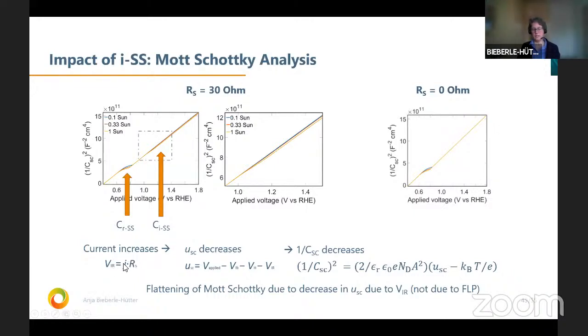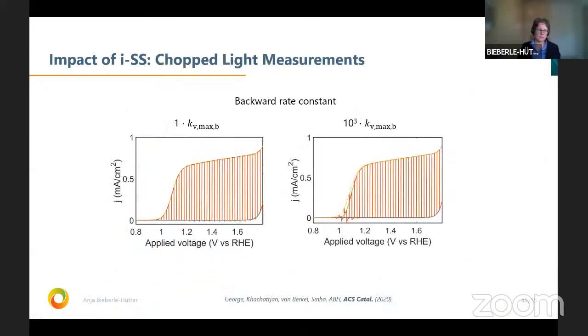So actually, when we have a serial resistance and the current density increases, we actually increase the space charge potential. And this means that we change this capacitance here. So actually, this flattening that we have here from the Mott-Schottky is due to a decrease in the space charge potential, but it's not due to a Fermi level pinning. This is something that we can get out from these simulations, and in the experiments, it looks actually the same. Here we change, for example, the back reaction rate and see that we get spikes here where we do not get this here. It's also something we can change in the simulations, but not easily in the experiments.